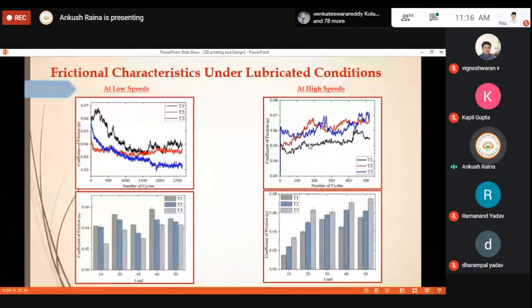In that case, we have used an oil, and you can see the curves are much more smooth in comparison to the previous dry cases. This is for low speeds, 100 rpm. These results are for high speeds. You can see that the curves are stable, and the coefficient of friction decreases with the increase in the number of cycles. And here you can see that the texture T3 has given us a minimum coefficient of friction.